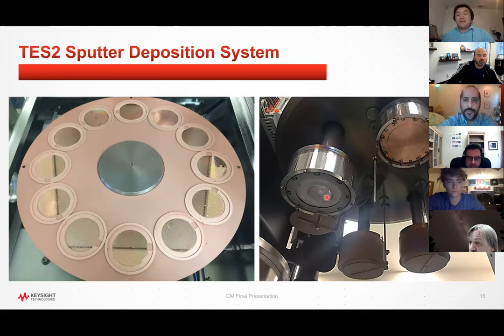The reason that this is just an R&D tool is that with smaller targets, your uniformity across the wafer will suffer. Typically, you want your target to be noticeably bigger than what you're trying to deposit on. So on the R&D tool, these targets are only 4 inches. On the production tools, they're twice as big with an 8-inch diameter. And for Keysight in particular, that whole fab is built around working with 3-inch wafers. Different companies might work with bigger substrates, but 3-inch, mainly because gallium arsenide and indium phosphide are particularly fragile. So it's a lot more difficult to work with bigger wafer sizes with those materials.